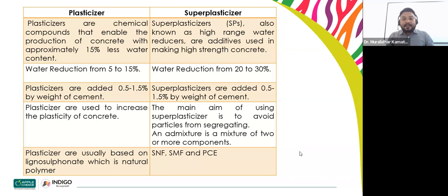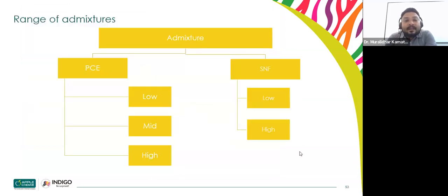And then your PCE bases will be there for water reduction, or one more will be there for slump retention. Slump retention means after 3 hours you have to retain 100 slump, 200 slump, or free flow concrete. For that we require adding this type of admixture. The range of PCE will generally be low, mid and high range, depending upon your requirement of slump and mechanical properties or compressive strength. Nowadays the precast industry is asking for 10 hours strength. After 10 hours they require 15 MPa or 20 MPa because of lifting strength. They are going to lift the precast panels, so their requirement is like that. And SNF will be low and high, there is no mid range.